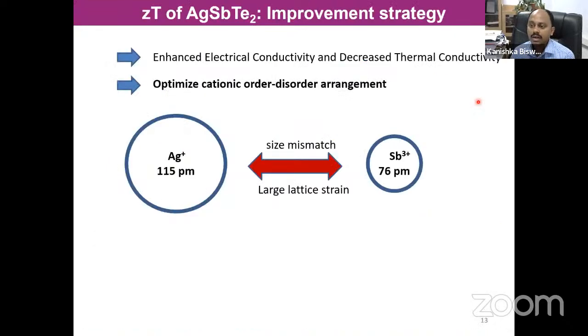Now silver is +1, with a size of 115 picometer, and antimony is +3, with 76 picometer. You forcefully put these dissimilar charge and dissimilar size atoms in the sodium position, which is an octahedral position. They don't like that position. They don't fit in this position, and they jump around each other and become disordered. That is the chemistry behind it. Their dissimilar charge and dissimilar size make them disordered.